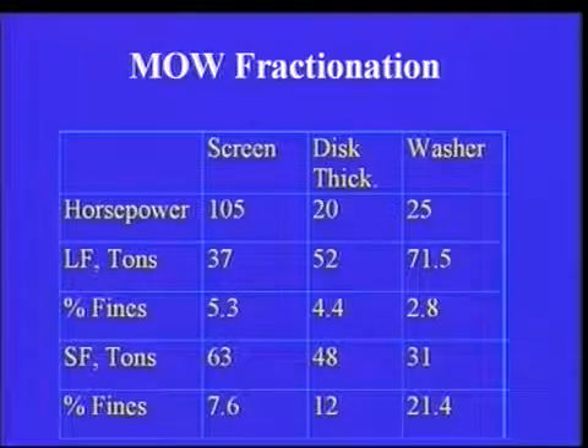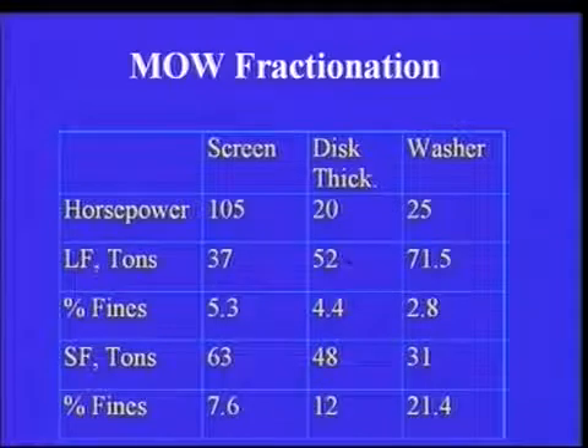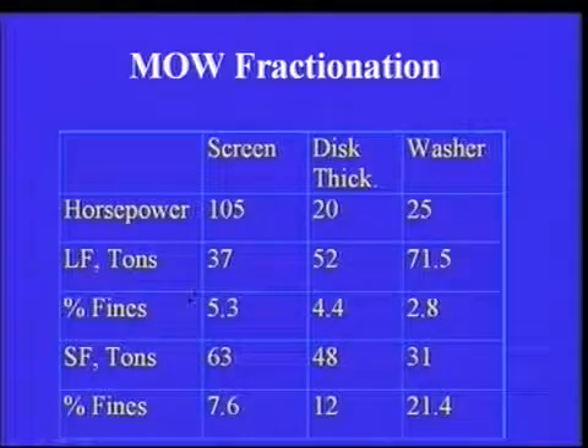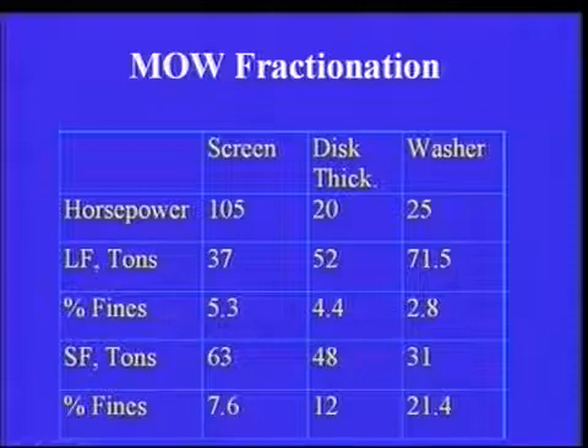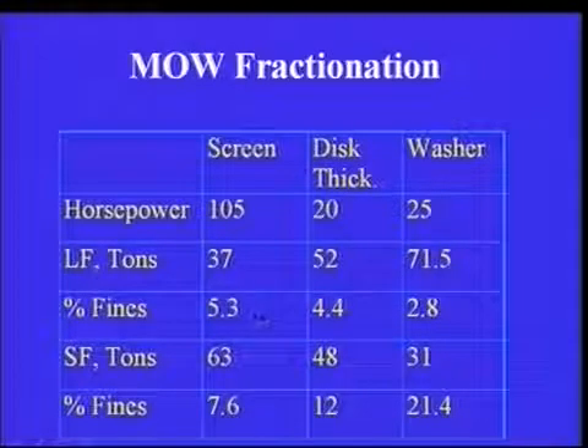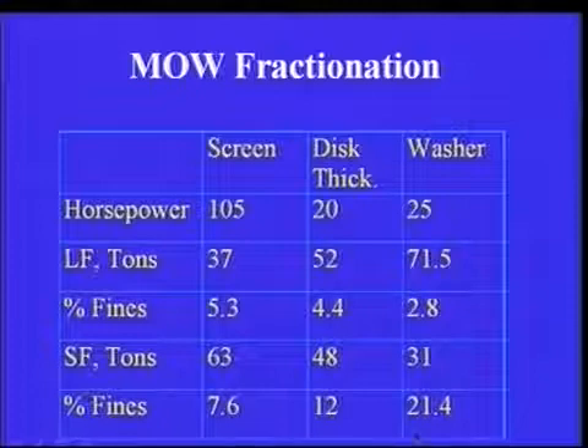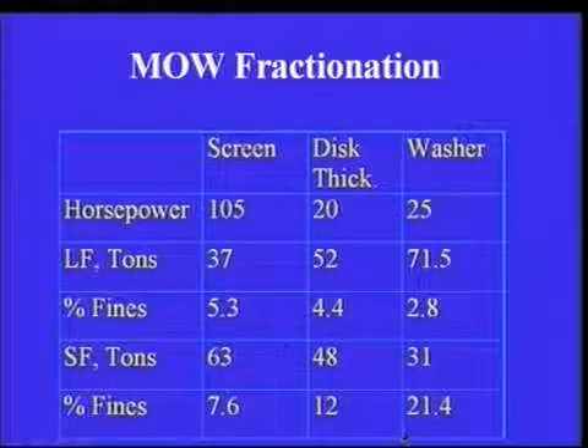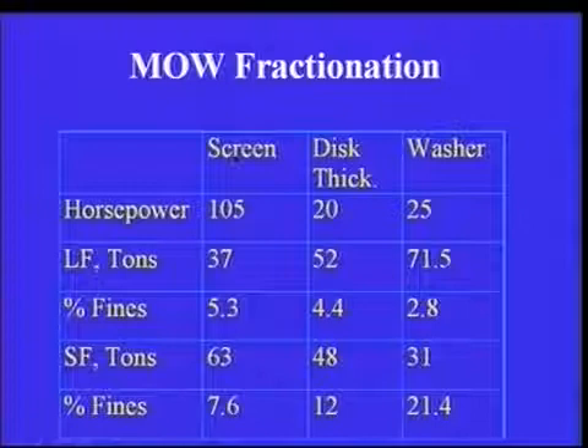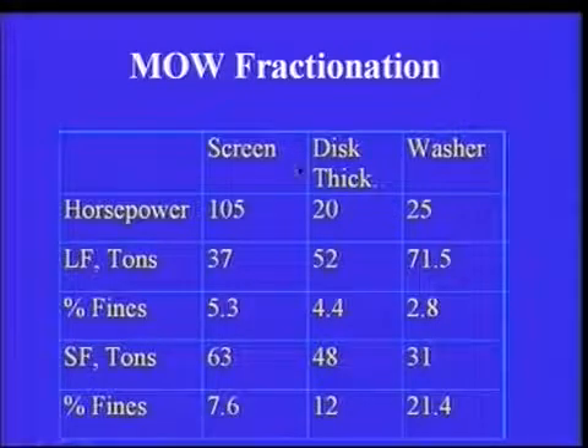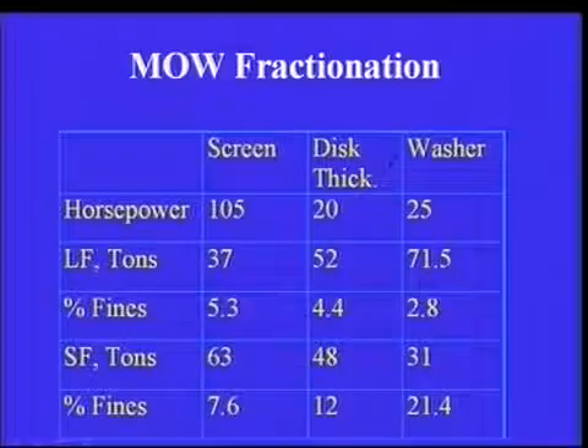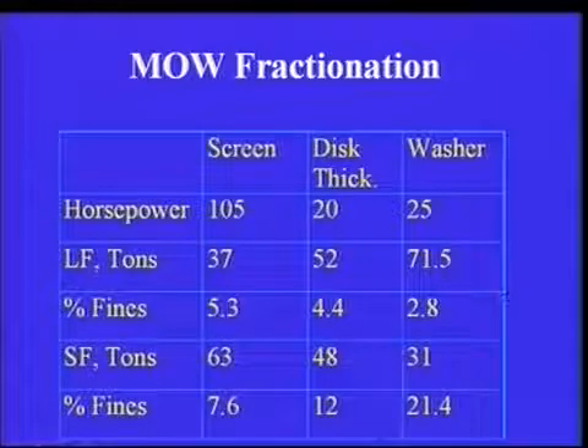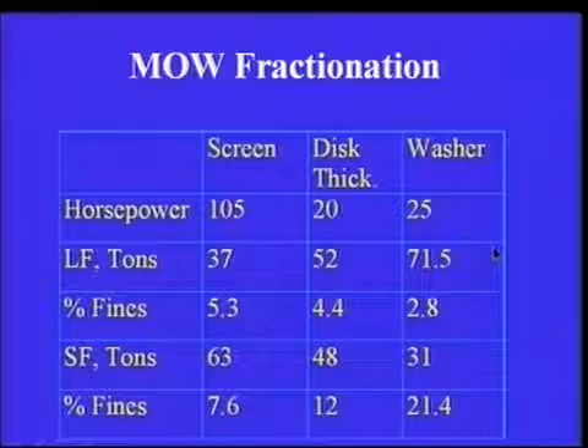Here is another example of mixed office waste fractionation. The amount of fines in the long fiber fraction can be anywhere from 3 to 5%, and the amount of fines in the short fiber fraction can be anywhere from 7 to 21%, depending on the type of equipment used for removing the fines. If we use the screens versus the disk thickener versus the washer, we can see the washer is the most effective in separating the fines from the long fiber fraction.